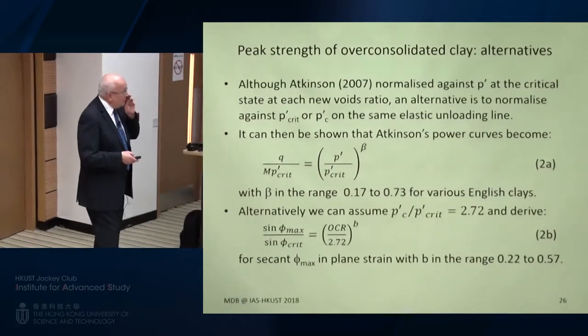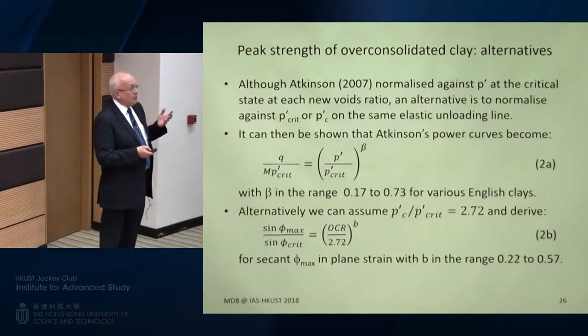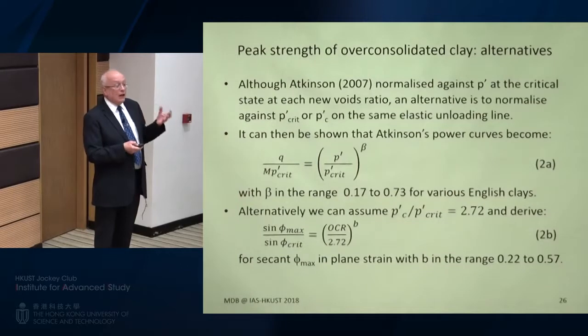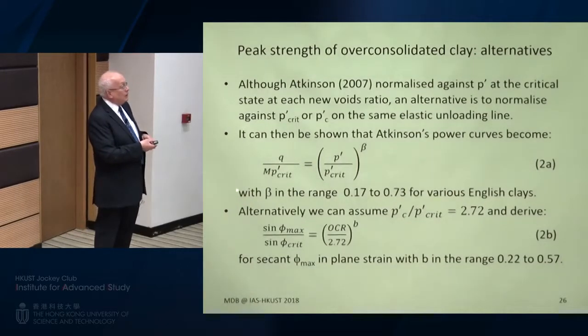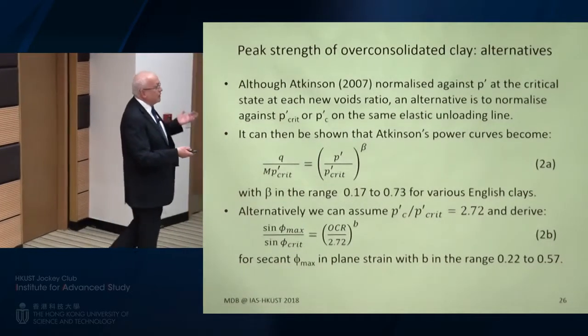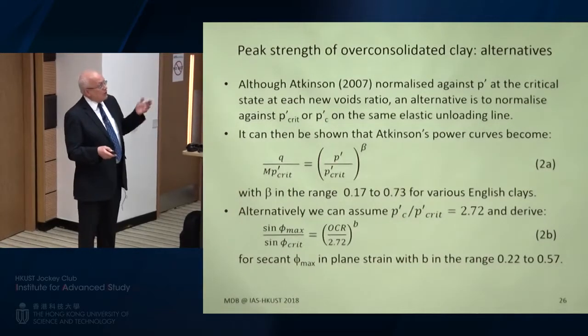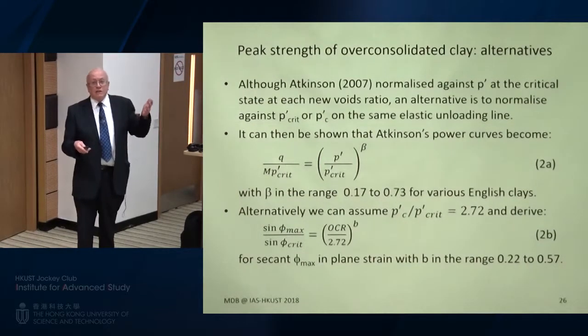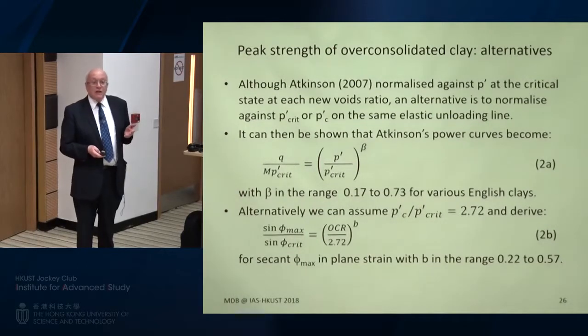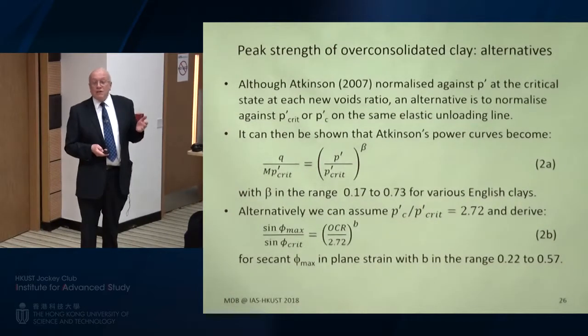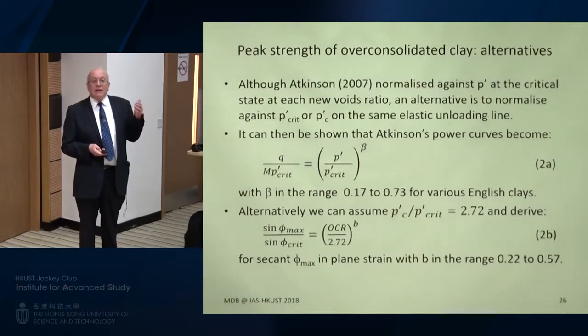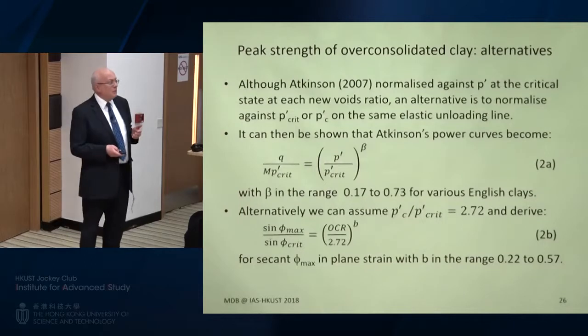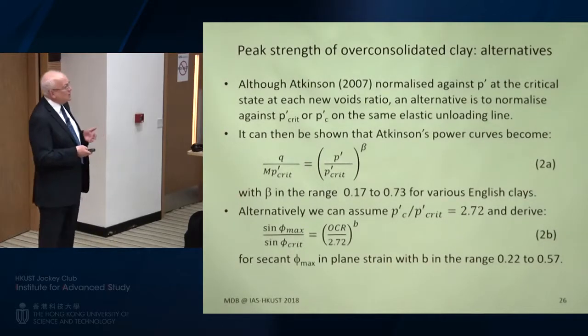So depending on the geometry of the fabric of the clay, the particular clay, you would expect different beta values. And I found that you could also express it in terms of a ratio of sine phi max over sine phi crit. And so there are these other expressions, any of which you can rely on, but sands and clays being really very similar in the data, and hypothetically at least, very similar in the reason for the data being very similar.